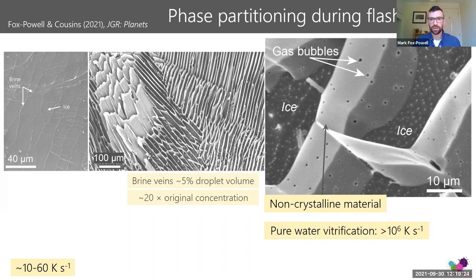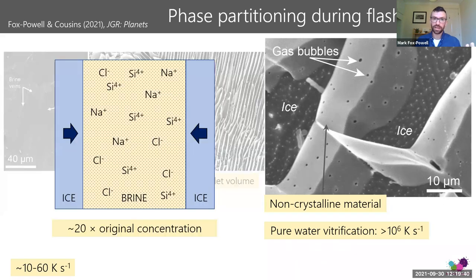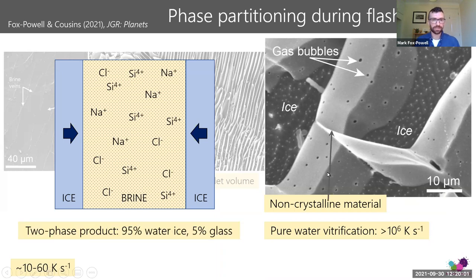Now, in order to vitrify, to form glass out of pure water, you need cooling rates of something like 10 to the 6 Kelvin per second, which of course is far more rapid than those we achieved in our experiment. But as you concentrate down this brine into this freeze-concentrated solution between ice crystals, ice grains, the high level of solute can make the conditions within these brine veins much, much more favorable for vitrification, and kinetic inhibition of any crystal formation.